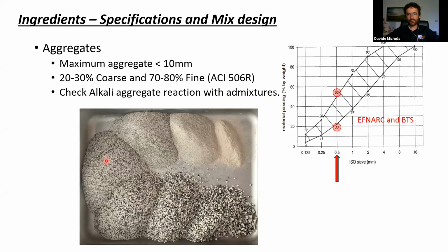You see on the right image the EFNARC scheme that gives us some indication of which part for each size of the particle we can keep. For example, for 0.5 millimeter, we have to keep in a range of between 22 and 50% of the passing.